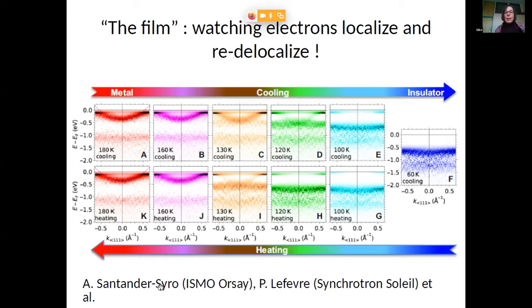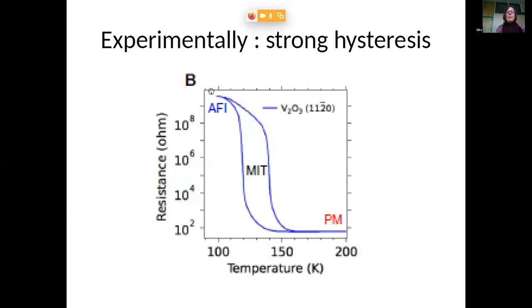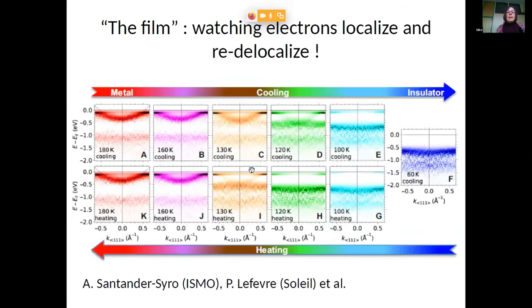Okay, why do you cool down and heat up again? Because, as I've mentioned before, it's a first order transition with a strong hysteresis. So that means on cooling or heating, you have somehow a delay. So you start here at 180 Kelvin in the metallic phase with a nice A1G orbital, which is continuously losing weight when you cool down here. Now you're losing it here. Okay, something still here. And you're in the insulator.